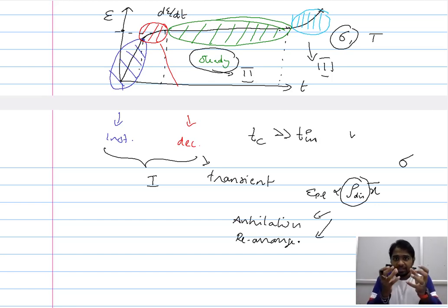So therefore, if you want to relate what happens in the steady state condition to a generalized behavior, what happens here is recovery. In the case of the transient creep or the decelerating creep, you have a dominant strain hardening. In the case of the steady state condition, you have a balance between strain hardening and recovery. So whatever dislocations the stress introduces, because of the temperature, the annihilation and the rearrangement reduce this dislocation density. Therefore, the plastic deformation is minimal.